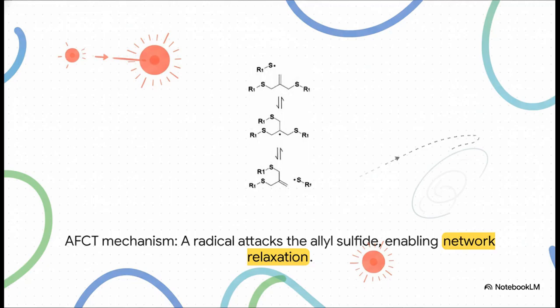Okay, here's the play-by-play. Researchers put a special molecule containing an allyl sulfide group right into their resin mixture. Now, during polymerization, you have these highly reactive things called radicals flying around. One of these radicals can come in and attack the allyl sulfide group. When it does, it temporarily breaks a bond in the main polymer chain. That's the fragmentation step. But here's the cool part. Instead of just breaking things, the bond almost instantly reforms, but often in a new, less strained spot. This little swap allows the whole network to subtly rearrange itself and just let go of that built-up tension.